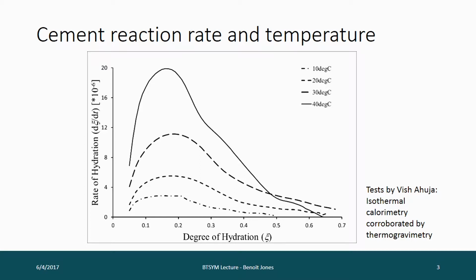So here's an example. These are isothermal tests. The specimens of cement paste in this case have been kept at constant temperatures of 10, 20, 30, 40 degrees. Along the x-axis, you've got degree of hydration, which is a measure of how much of the chemical reactions between cement and water have occurred. So it goes from 0 to 1. Most concretes never get to 1 because it's virtually impossible for all the cement to hydrate. And on the y-axis, you've got the rate of hydration. So that's the rate at which the chemical reactions are occurring.